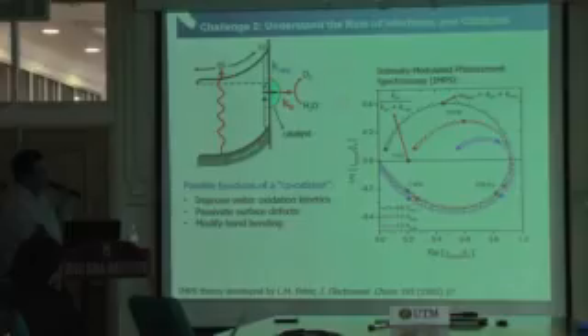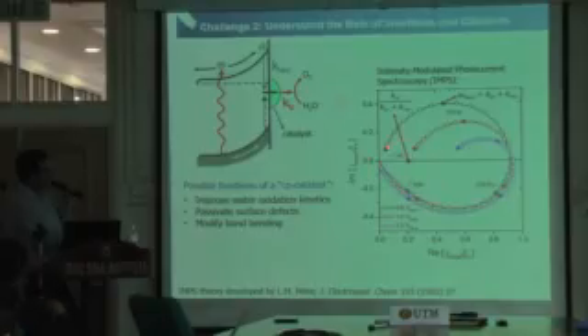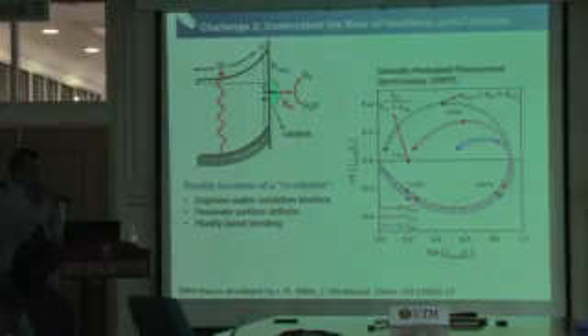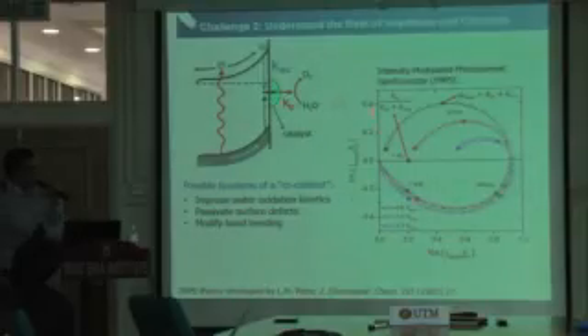Now, if we scan the frequency, going from high frequency to low frequency, we can lock in this modulated photocurrent, and we really look into this modulated photocurrent part. We can then have a complex plot of photocurrent. This is the imaginary photocurrent, this is the real photocurrent, and the frequency axis is not shown but is actually inside here. It's going from high frequency here to low frequency. So this is similar to electrochemical impedance spectroscopy. Basically what this plot says is whether this modulated photocurrent is leading or lagging the modulated illumination. Right? So it's just plotted in a complex plot. This is high frequency, this is low frequency here.